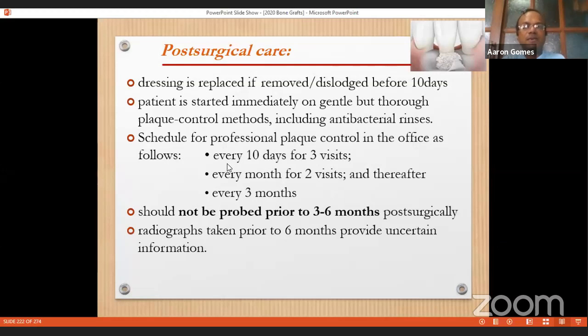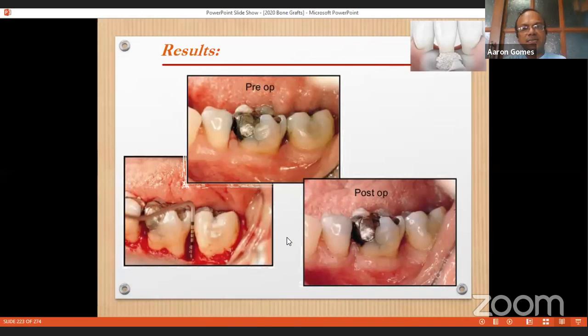After that, you will call the patient for 3 visits every 10 days. That is the first month. And then every month for the next 2 months, and then every 3 months thereafter. Remember, the site should not be probed prior to 6 months, depending upon the type of graft you have used. Most of the xenografts take about 9 months for integration. The cancellous grafts take about 3 to 4 months. The cortical grafts, as you've seen, take around 6 months. So radiographs taken prior to 6 months may not give a good result.